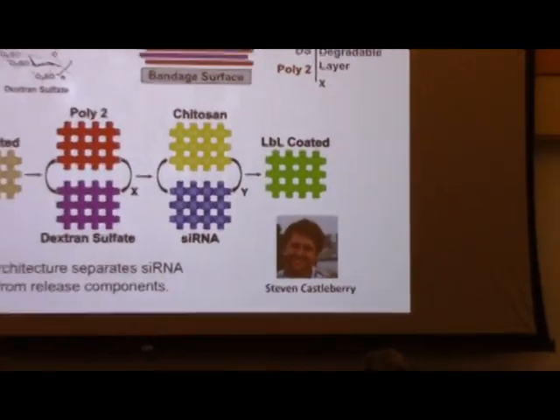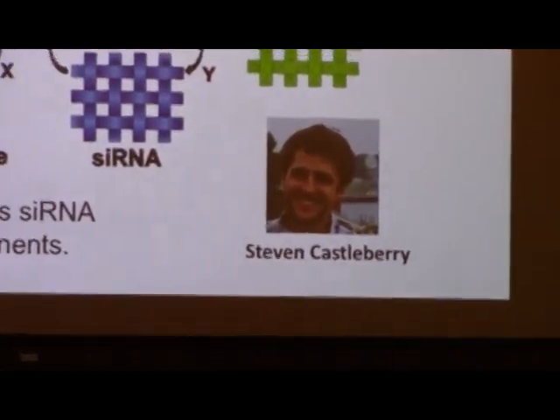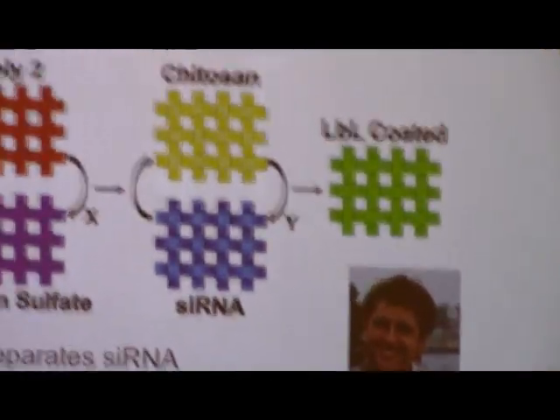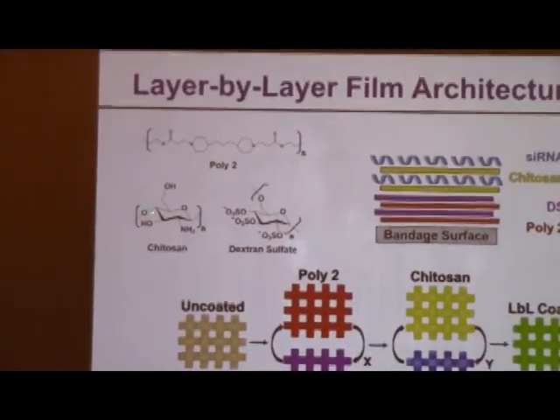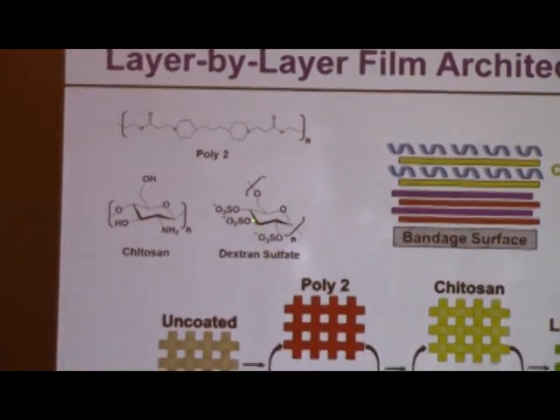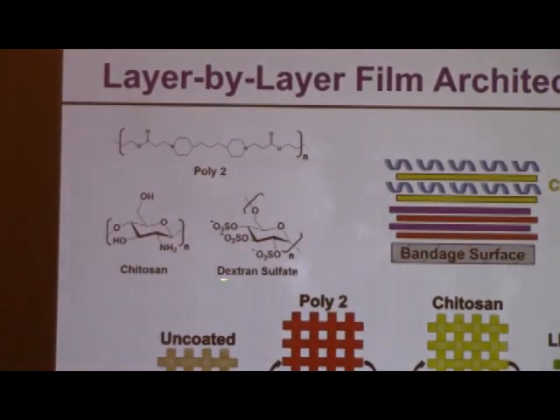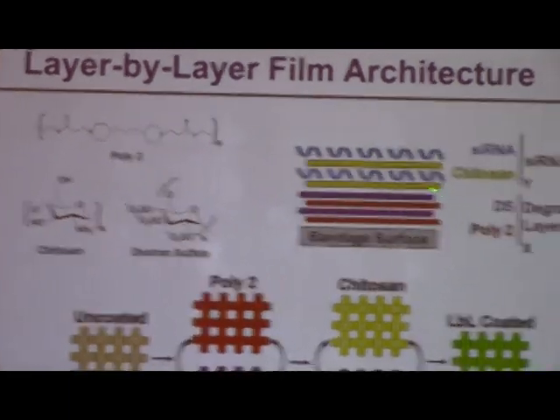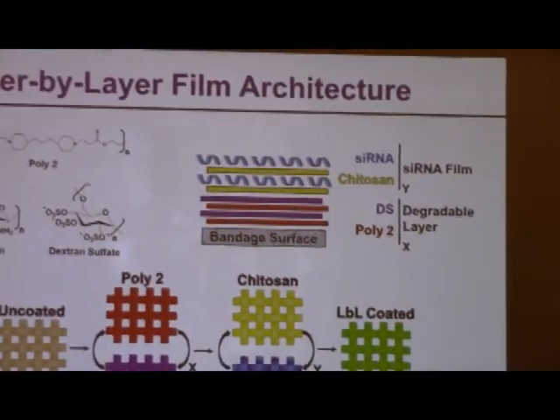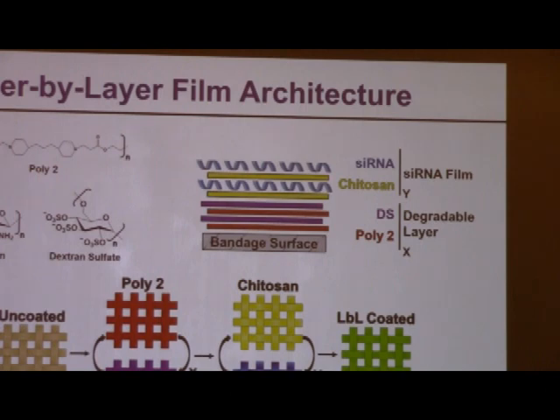Stephen is now working in industry in Chicago. Now in this work, he's generating layer-by-layer films, but he's actually doing two different kinds of films. He found that a very simple polysaccharide known as chitosan, which is derived from crab shells and has these positively charged amine groups on it, works very well in layering siRNA, which is strongly negatively charged. So he can make siRNA and chitosan multilayers, and these layers will be very stable. They're very effective at protecting siRNA.